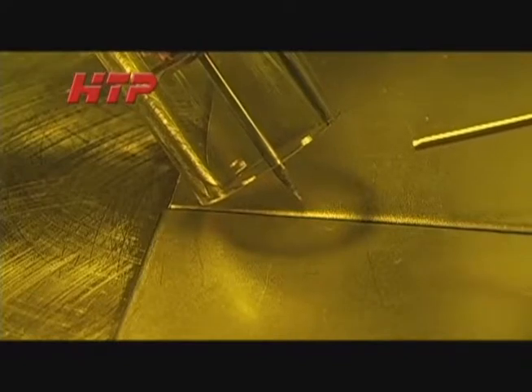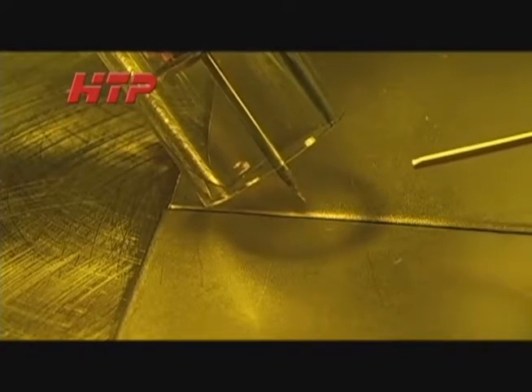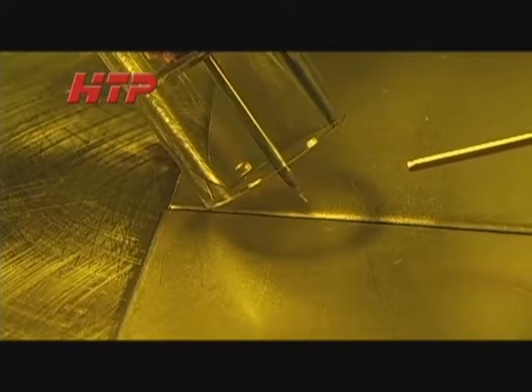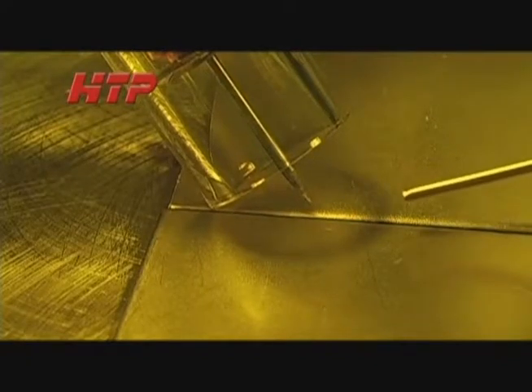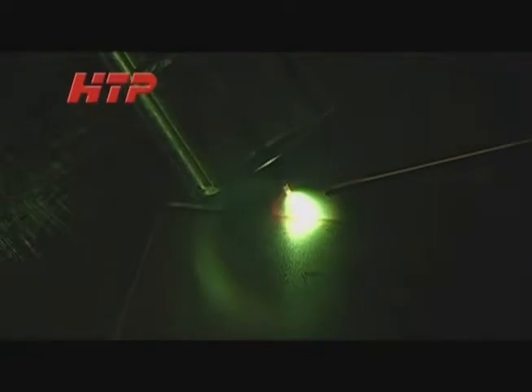edge. We are going to butt weld two pieces of 18 gauge steel together. 18 gauge steel is 48 thousandths of an inch thick. We will start by tack welding the coupons together so they don't warp.